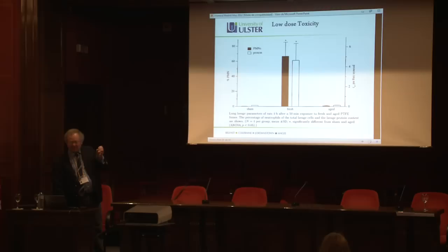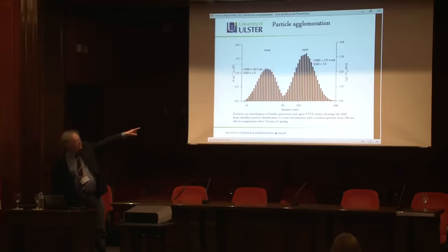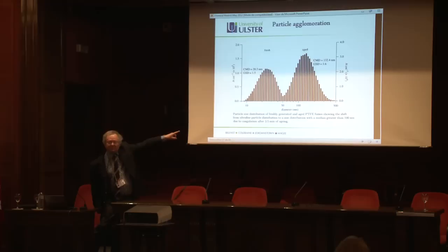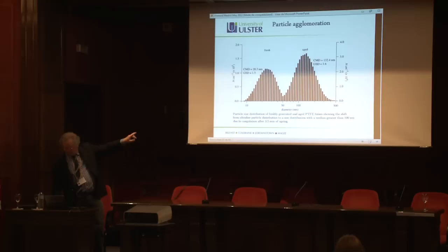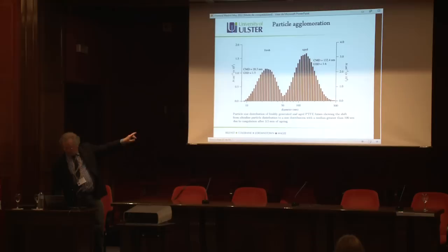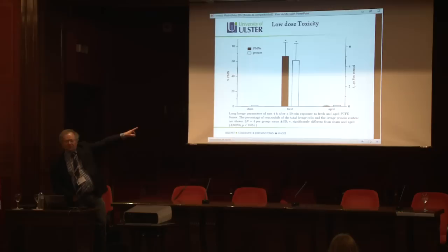Gunter Oberdörster heated Teflon to 550 degrees and produced an aerosol of PTFE. The fresh aerosol contains very small particles; after about three minutes, the size distribution shifts to larger sizes due to agglomeration. Animals exposed to the fresh smaller particles showed acute toxicity — some died acutely. Again, this size phenomenon is related to surface activity and reactivity, and a common outcome is inflammation.